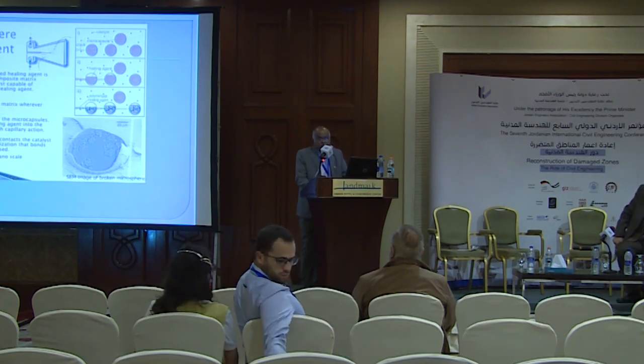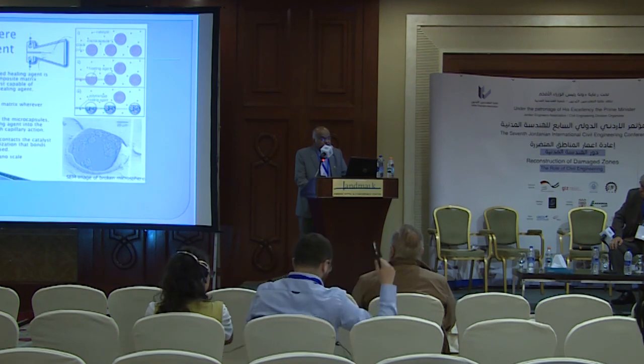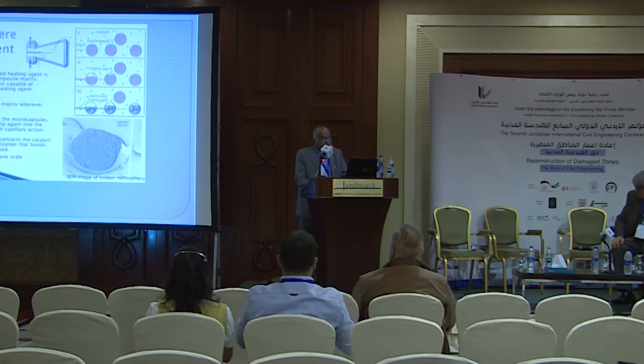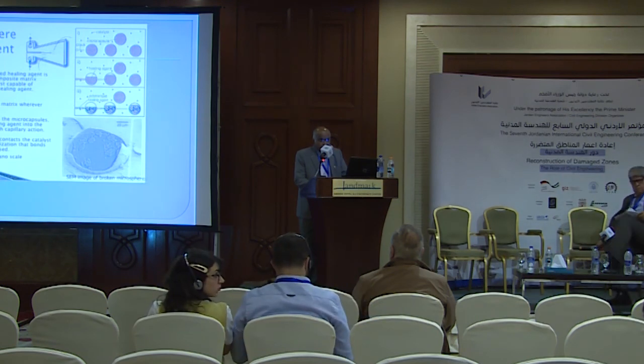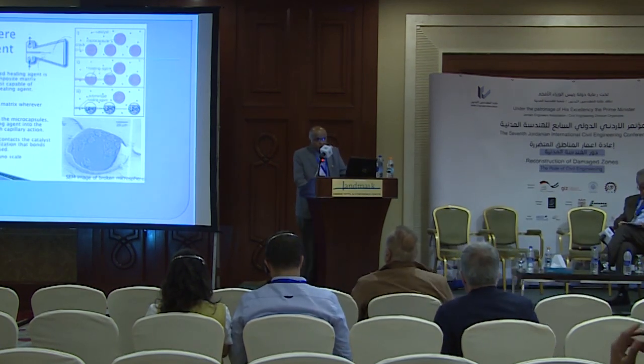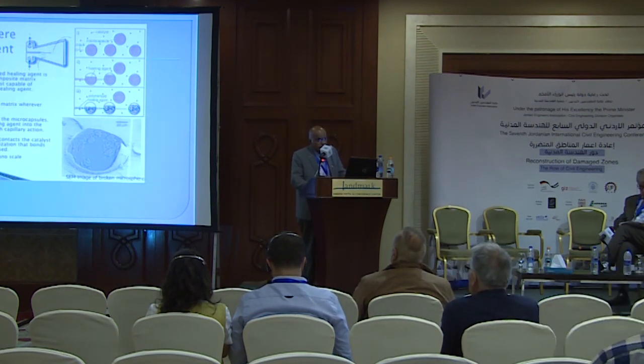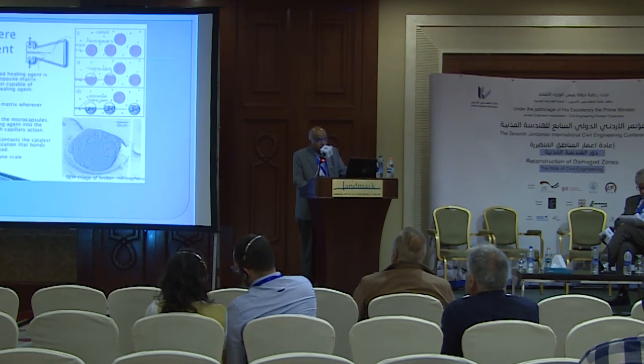So what is this self-healing composite? This slide will show you what the basic structure or microstructure of such a material is today. We have a healing agent which is embedded in the matrix. So what happens is when a crack forms in the material, these capsules break and the healing material comes out and goes to the crack by means of, as you may know, Darcy's law, that is a pressure difference, pressure gradient. It automatically finds its way, like water finds its own level from high to low. This material will heal itself by means of the flow of the embedded agent. So this can be super glue or some other compound which hardens in contact with the catalyst which is in the matrix.